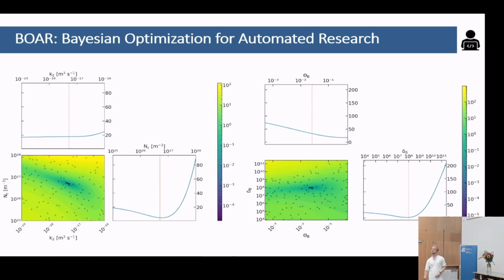Here are some examples. I don't think you'll be able to see that so much, but basically this is the same as presented before, where here you had 2 free parameters. You have a very narrow solution. That one is actually correlated. You see that slight kink. And this is with the figures of merit, where the minimum is so narrow that you can barely fit it, because it's a very, very small and very steep minimum.